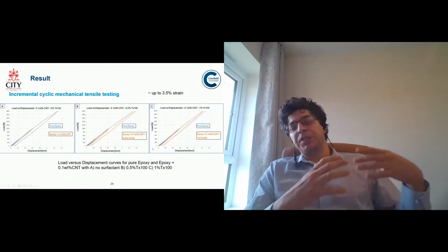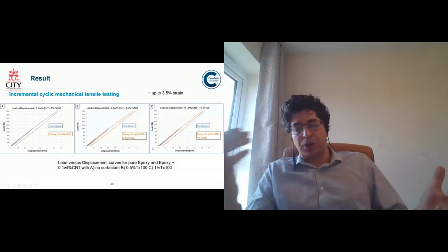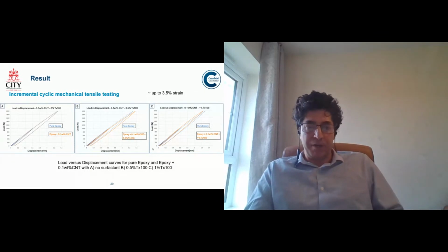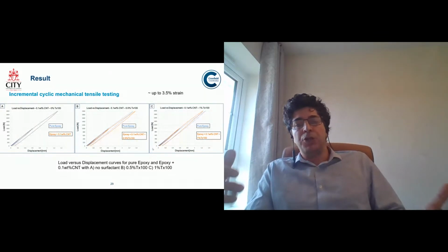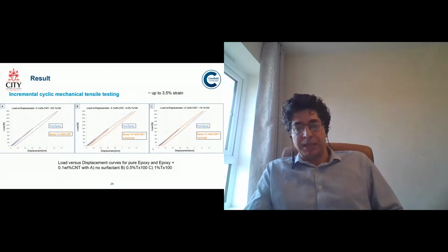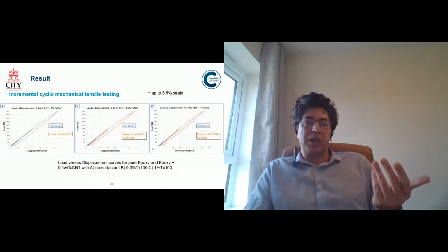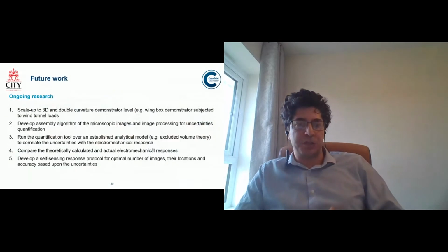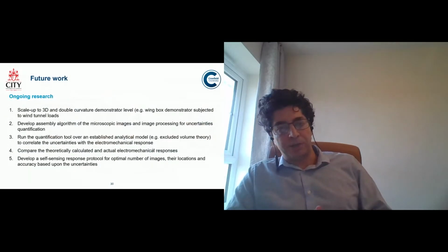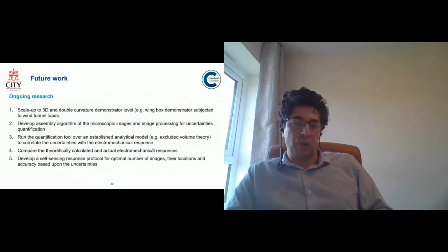So maintaining the design limit loads in a structure, which is a high performance structure, and people are very, very concerned about changing that, you would be able to achieve a sensing capability easily. And you haven't added really anything to the weight or the thickness of the material if you use that. That's where we're doing research to come up with a 3D double curvature demonstrator level, and we're focusing on the wing box demonstrator now, to make it fully from this smart structure and test it in the wind tunnel at the University of London.